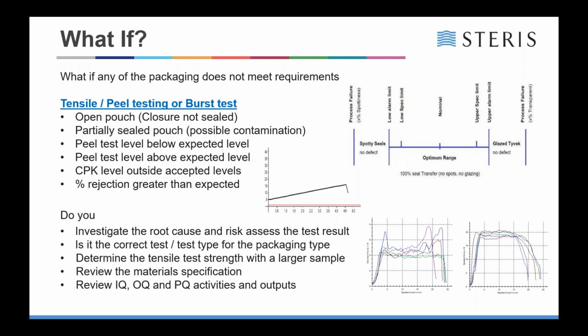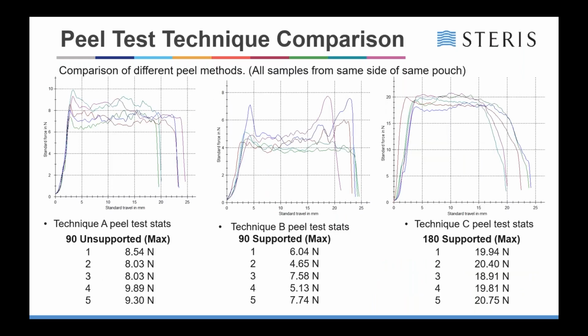There are other occasions where you need to look at the actual test method that has been used. Take, for example, if you use the likes of technique A, and you're getting test levels of around 7, 8, 9 newtons. If you test the exact same samples using 180 degree supported, you'll get 18, 19, 20 newtons from the same samples, from the same pouch. But if you use technique B, you get a significantly lower level. So you need to be careful about which methods you're using.